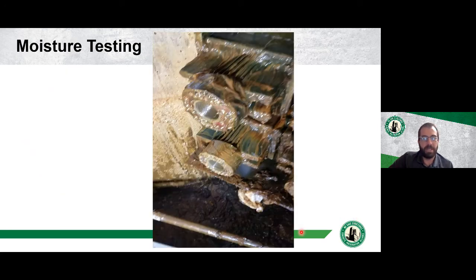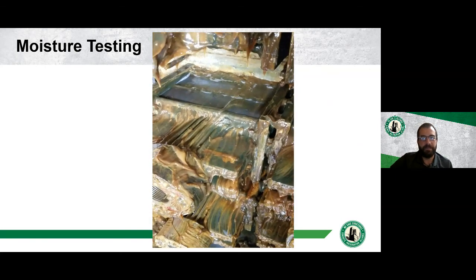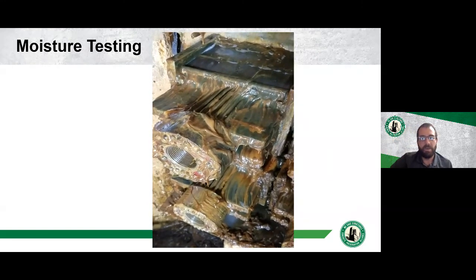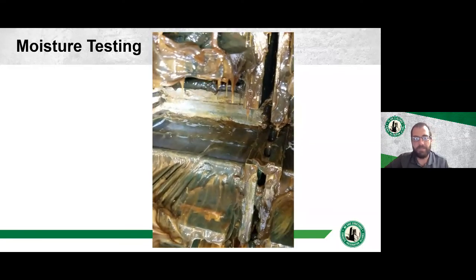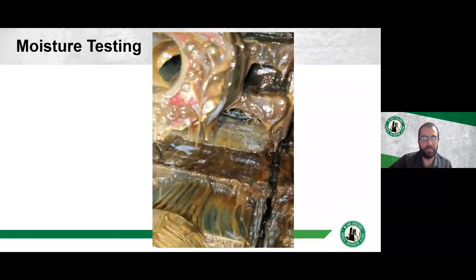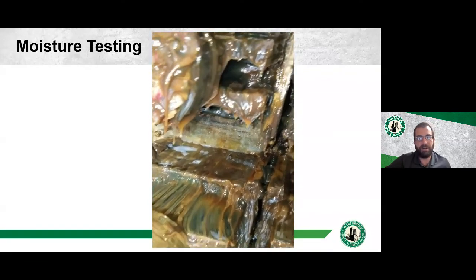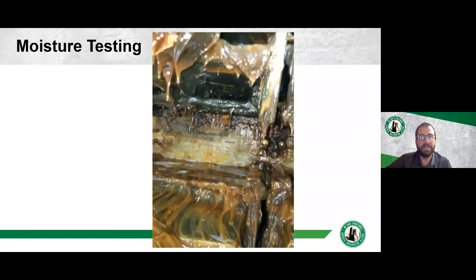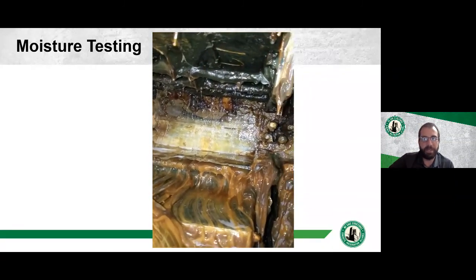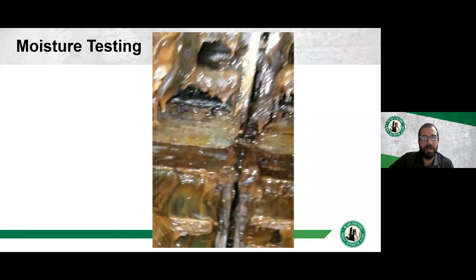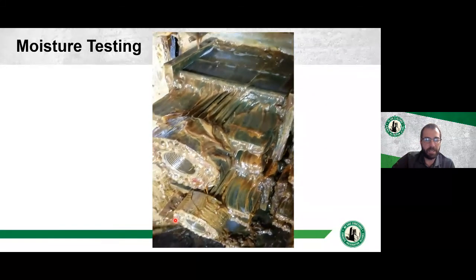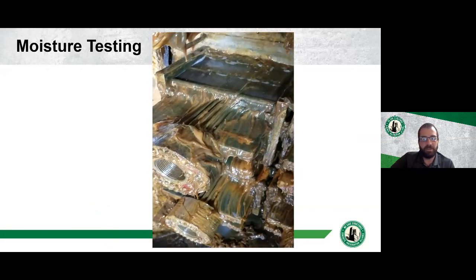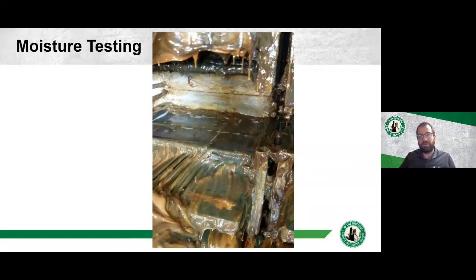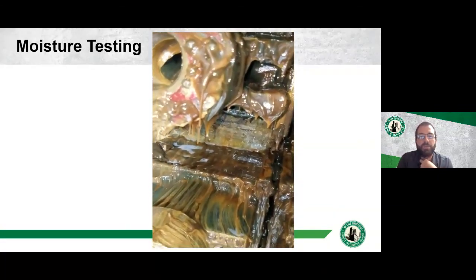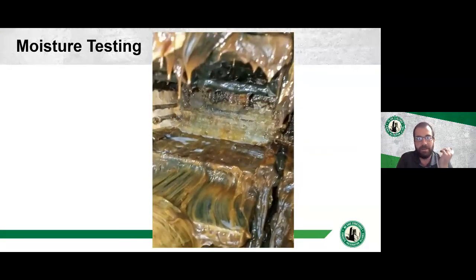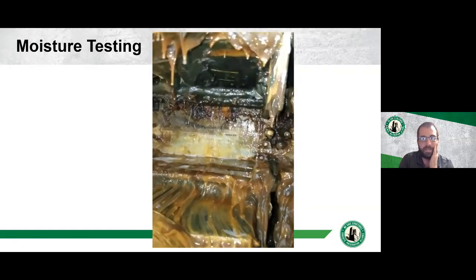One thing we also did was look at, is there moisture in these tendons? So on the opposite side at the other anchorage, we put pressure on. They have greasing ports, so they have a little greasing port that we connected onto, put pressure onto it, and pushed air across, and we can see that there is dripping water coming out of these anchorages. As we put the pressure on, we were pushing water out from the other side. I'll replay this video here, but you can see dripping water down here. So effectively water is getting into these anchorages. Even though they're well greased, water is still getting in there. And so that can lead to corrosion of those cables. So obviously protecting these cables from water infiltration is really critical to the durability of this structure.